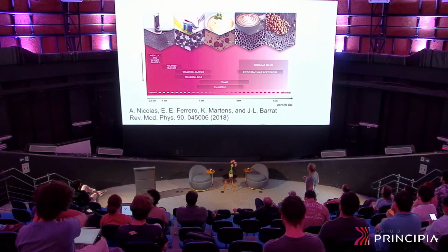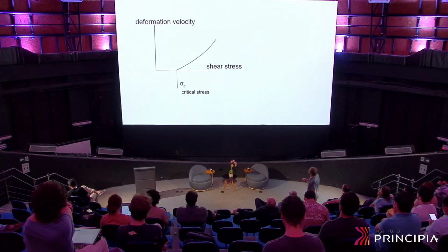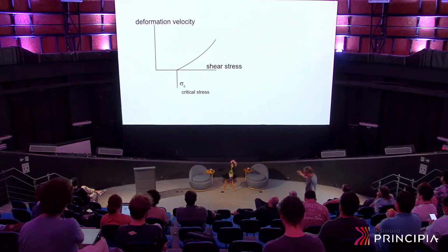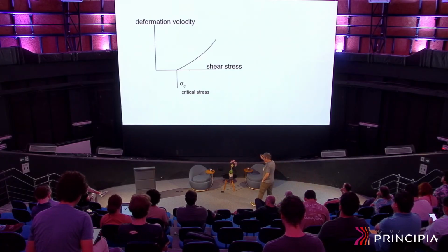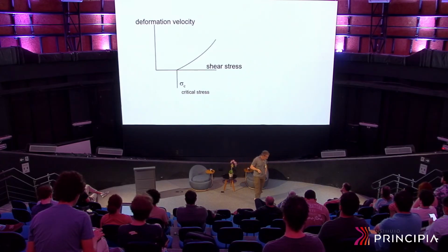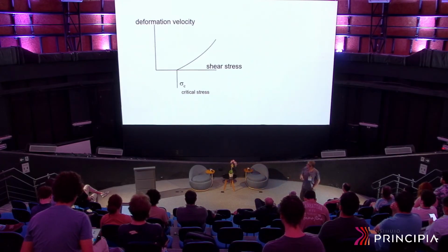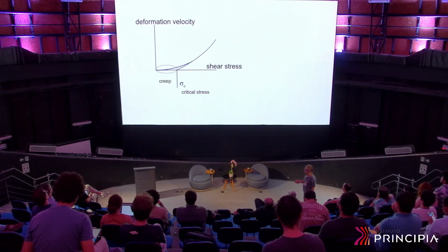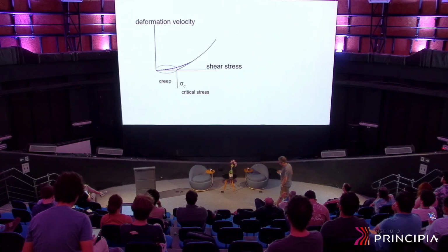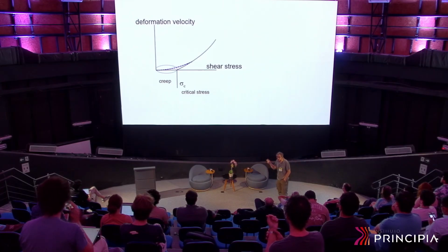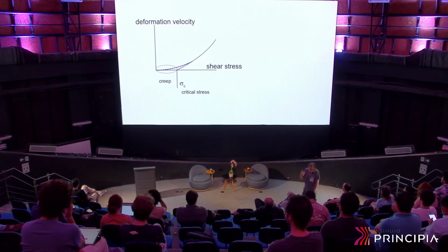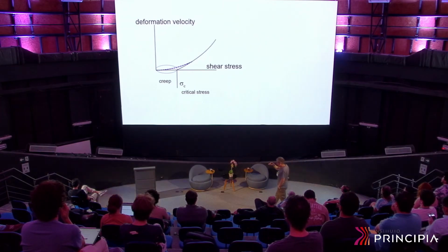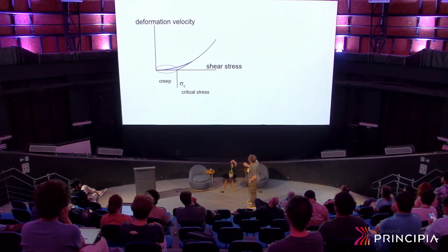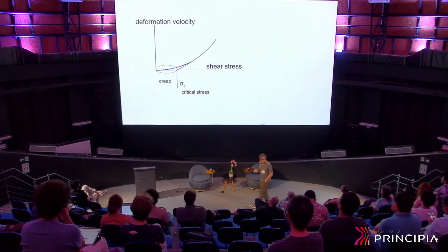And the thing is, in fact, that these kinds of materials, this is the plot that I put before, the deformation as a function of yield stress. But if you think of the problem of soil creep, or even more general abstract problems that people have been considering for many years, it happens that there are mechanisms that make this material flow somehow below the critical stress. These are typically called creep phenomena, and there may be different reasons for this. We thought that probably this problem of soil creep is related to some way of creep that occurs below the critical stress that is indicated here.